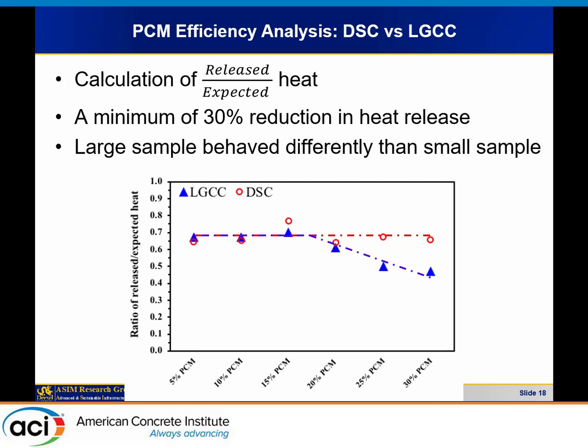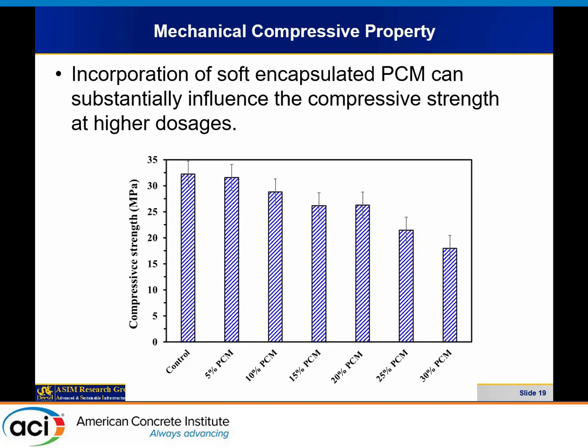At some point, about 17%, we get that bilinear effect, and it deviates from the DSC work. It might be because of the interaction effect of the amount of PCM that we put in. Because we put lots of these reservoirs, this PCM, inside the concrete, you might have some interaction between them, so you don't get that much of an effect at a larger dosage.